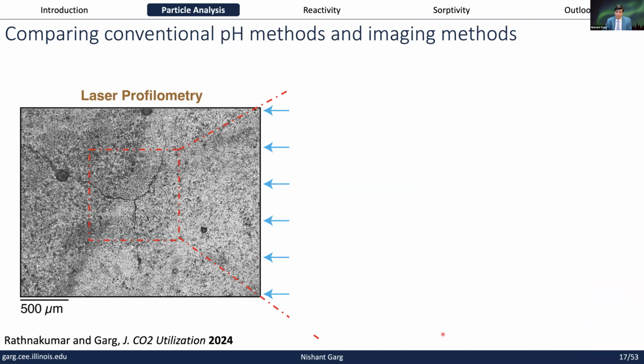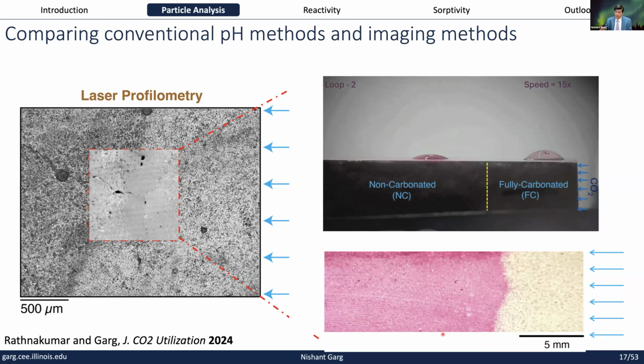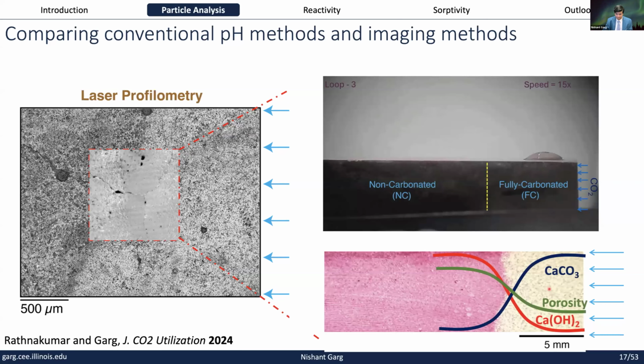I'm going to maybe play this video again so you can just see it. You can see on the fully carbonated zone, the droplet is not fully absorbed, which we infer as that area being highly dense and of low porosity, which makes sense because that stops the ingress of CO2. Now, from a durability point of view, this is great because we don't want that CO2 front to move. However, if your goal is to actually sequester CO2 and get as much of that CO2 in, then this system is not good. And again, this was a pure OPC system; with different SCMs and different binders, things could change quite a bit. So again, we now get the full evidence that there's indeed a porosity reduction in this carbonation front based on these methods.